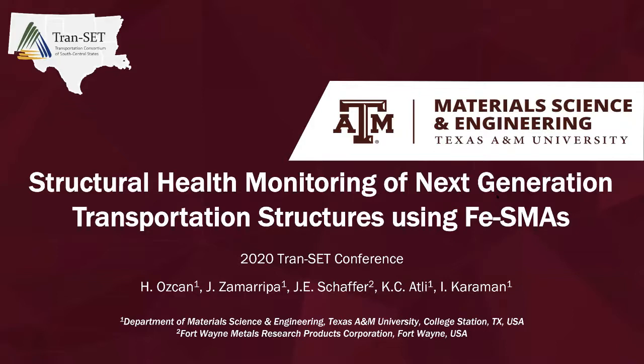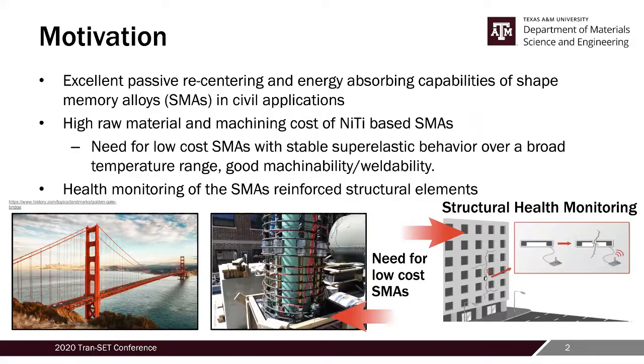This particular alloy is very interesting because it can recover large amounts of deformation. This is a property of shape memory alloys, which can recover large amounts of deformation compared to a conventional stainless steel. For example, conventional stainless steel you can deform up to 0.2%. However, with shape memory materials, you can get recoverable deformation up to 10%. So this property makes these alloys very attractive for transportation structures. Besides these properties, SMAs, shape memory alloys, can provide recentering and great energy absorption capabilities.